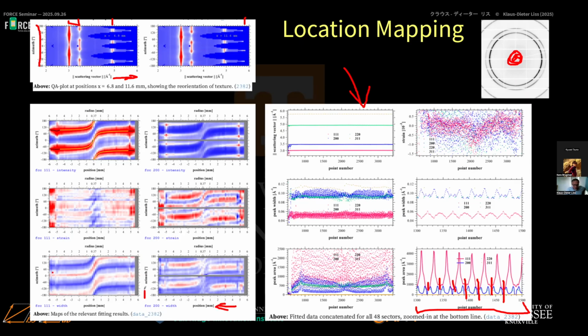an azimuth plot, map, let's say, yeah, where I plot here the intensity in the first row. Here I plot the strain, and here plot the width. And we see they're all very anisotropic with respect to the shear and the transverse direction. Or in the lab coordinate system, they have this S-shaped curve here. We can stretch that straight, and that's what we're doing as well. That's why we do the coordinate transformation. But this is half through raw data here. So we see the texture. Intensity is texture of the material for the 111 reflection, 200 reflection, and we have the others as well.